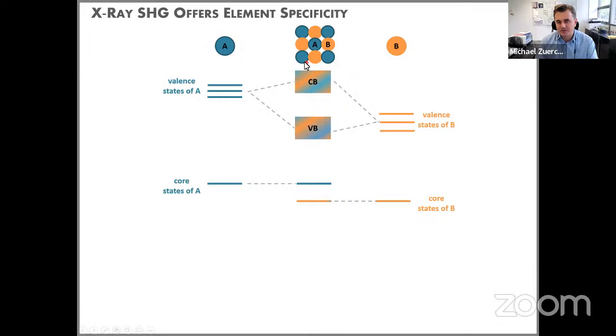I should say that this is not, of course, just forming a crystal out of two atoms. It can be n atoms, and it can also be an interface, such as a liquid-solid interface. In all these systems, these hybridization effects take place, and we end up with an energetic structure as exemplified here in this case. And those of you who are familiar with X-ray absorption spectroscopy or X-ray methods know that this is one of the key aspects we like to use in X-ray spectroscopy to do element-specific studies: to use one of these core electron resonances to probe transitions into these valence states.